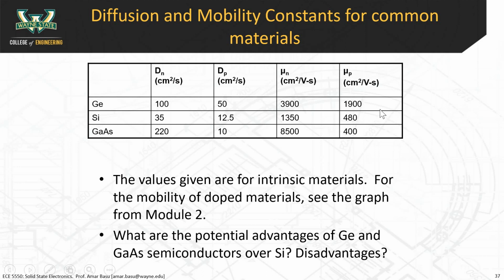Okay, these are the constants for germanium. One thing you can see here is that germanium has like 3x higher mobility of electrons than silicon does, and almost a factor of 4 for the holes as well. So germanium is a high mobility material, used in high speed electronics. The diffusion coefficients are also larger. Notice that the diffusion coefficients are proportional to mobility.